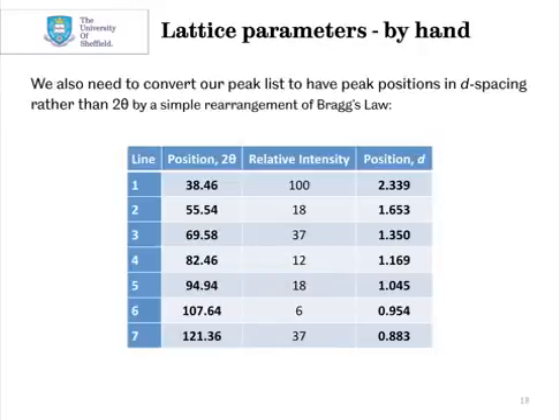We also need to then convert our peak positions from 2 theta into d spacing. This is done by a simple rearrangement of Bragg's law. Again, in the spreadsheet that I'll attach with this, you can see how I've done that in Excel. So our peak at 38.46 degrees 2 theta has a d spacing of 2.339 angstroms, and so on. So we've got a list now of our peak positions in d spacing.